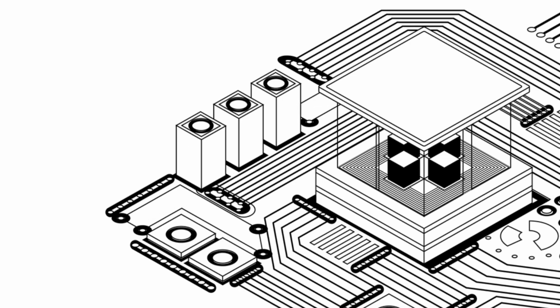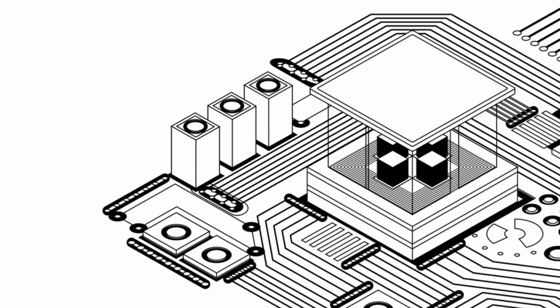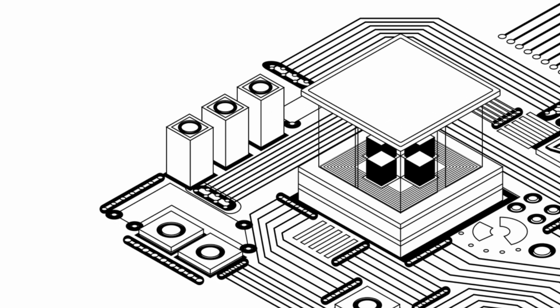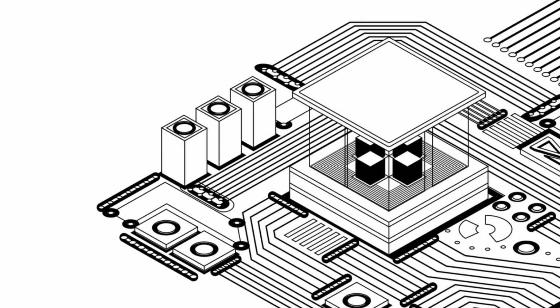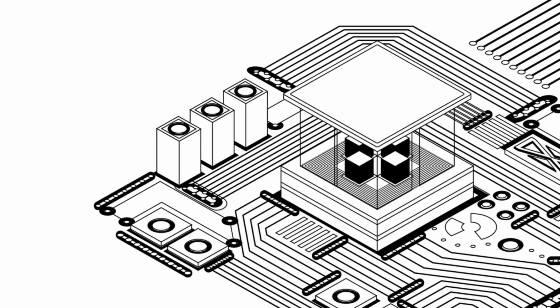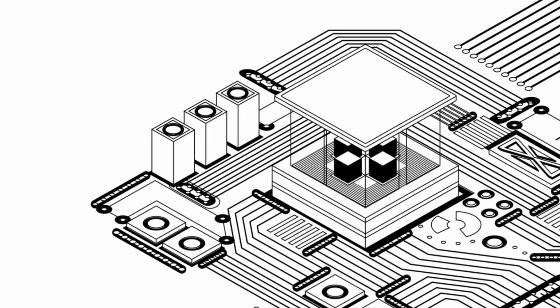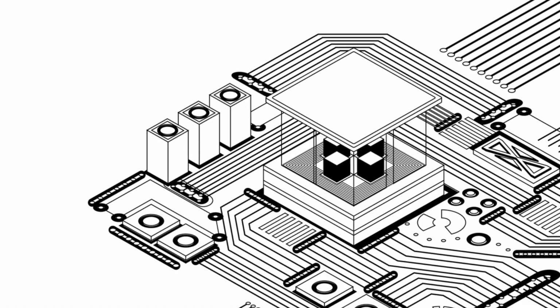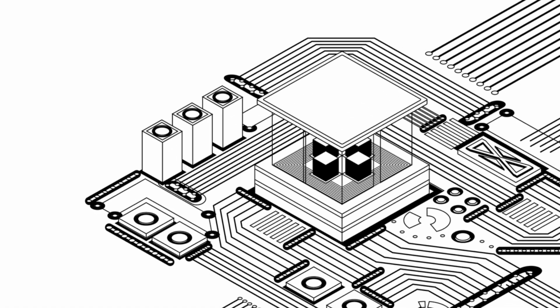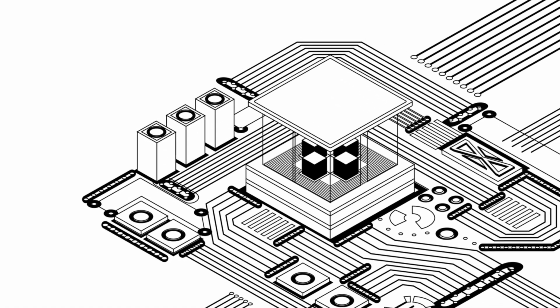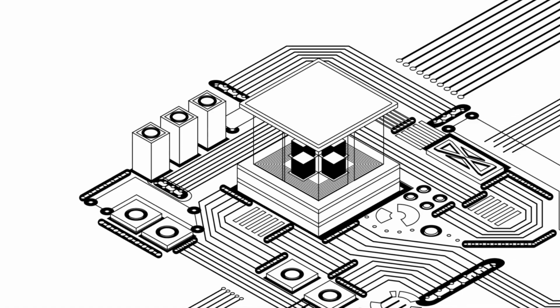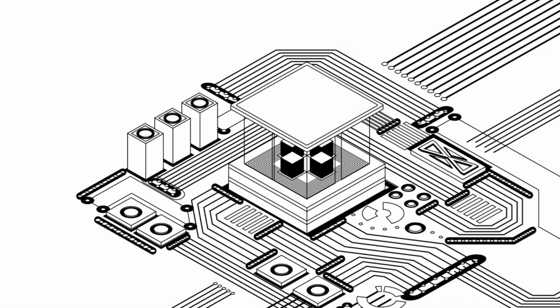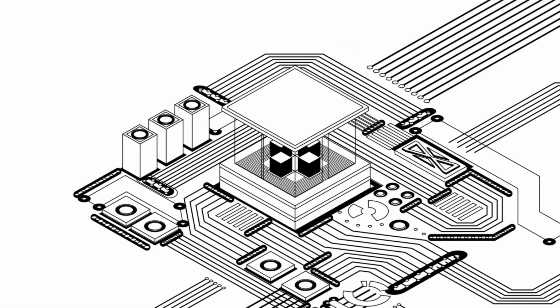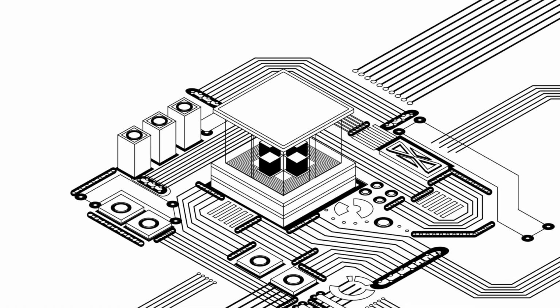Diamond's thermal conductivity removes heat from the GaN active layer 12 times faster than silicon, dropping junction temperature from 165 degrees to under 80 degrees C at equivalent power density. Result: 3 to 4 times the power density of GaN on silicon at the same junction temperature. Same chip footprint, same cooling system, 4 times more power throughput per unit area.